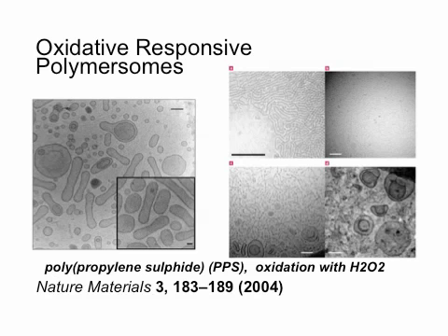You can start to make systems, if you're clever with your chemistry, that disintegrate. So here in this Nature Materials paper, you have a polypropylene sulfide as a hydrophobic block, and the sulfide groups you can oxidize, so you get sulfoxide, which makes it hydrophilic, and then suddenly instead of amphiphilic, everything is hydrophilic, which means you go from a vesicle type of arrangement to complete disintegration.